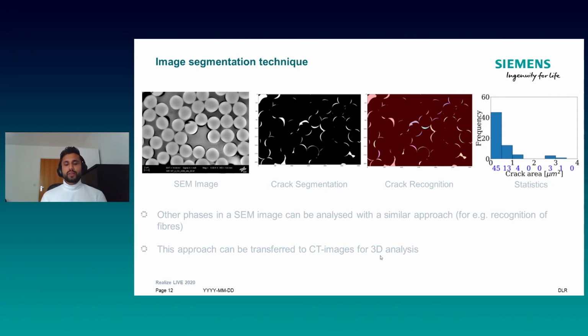And for this reason, we have written a Python script which detects the cracks in the matrix and then gives us a plot of the distribution of cracks with their sizes. There are commercial software packages available as well, but we use this technique for detection of fibers and then to detect circular fibers and so on. And this technique can then be transferred to 3D analysis as well, where we have a 3D stack of images.